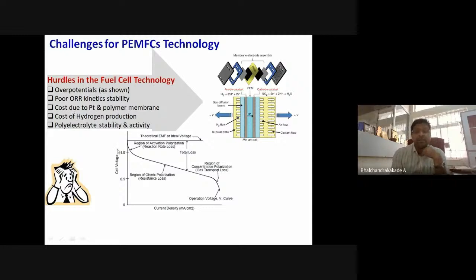So this is a typical IV curve of a fuel cell, where you can see the ideal curve, where we can expect 1.23 volt as the voltage of a fuel cell. But what happens in the actual case is that the curve looks like this. There are a lot of losses and eventually the voltage becomes very, very low, almost less than 0.4. Once it becomes less than 0.4, it's of no use. So there are several losses. There are three regions: first region, second region, third region. The first region is called the activation barrier or activation overpotential, because of the poor reaction kinetics.